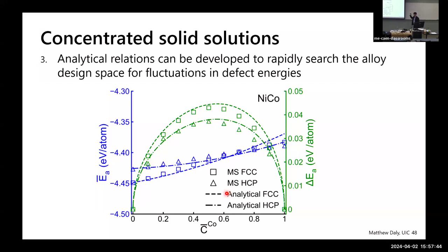So what I'm saying about deformation twinning, and I don't have a good explanation for this, is that in the materials I looked up in the literature, it causes this magic of just a flat, linear work hardening rate. If I was drawing the stress strain curve, it would look like that. And if you look at most of the high performance steels like TRIP and TWIP, that's what their stress strain curve looks like. That is magic in avoiding necking because you're building up stress, but you're not doing it so fast that you hit your true stress. So if you were plotting the derivative, it would kind of hit something like that.